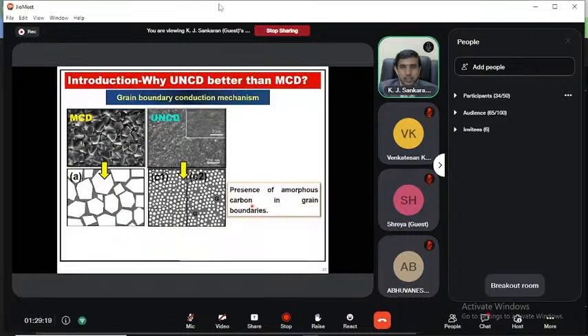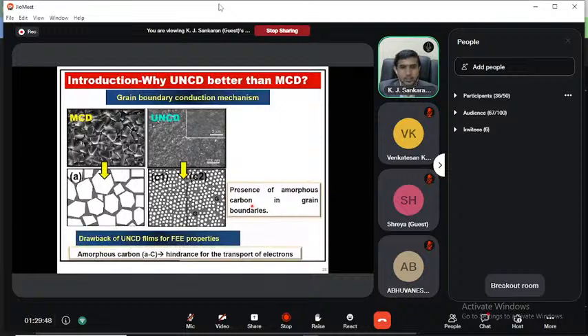So they derived a grain boundary conduction mechanism, by Professor Yin and Lin in Taiwan, and they found that the MCD films have very big grains with a lack of grain boundaries, so the electron emission is very much limited. But when you come to UNCD, it has very small grains, the aspect ratio is higher, and they are surrounded by abundant grain boundaries, which makes the UNCD highly conducting and a better electron emission material. But there is also a drawback: the UNCD materials have amorphous carbon, which is also not very electrically conducting, so that hinders the transport of the electrons.